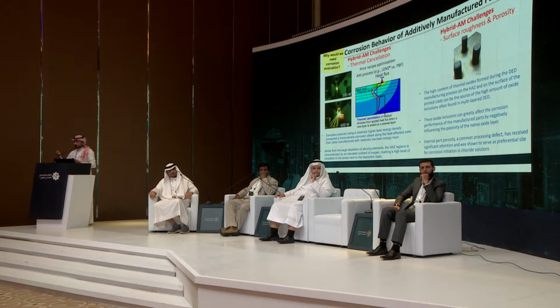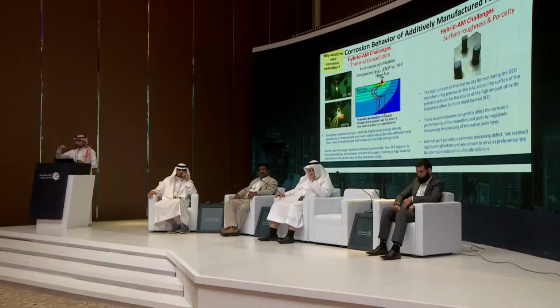How does hybrid additive manufacturing help in this way? What we can do is print, and then do the machining while we're printing. By doing so, we do grain refinement. We improve the surface morphology and surface topography as well. But also, we are maintaining the residual stresses. You see here the blue curve and the red curve. The red curve, when you print, you actually print with compressive residual stresses. These compressive residual stresses will resist the corrosion behavior.